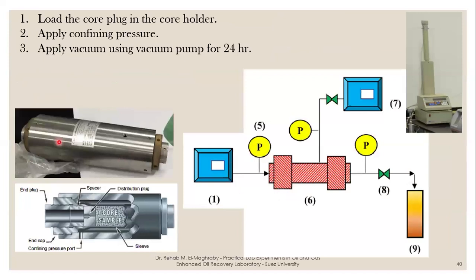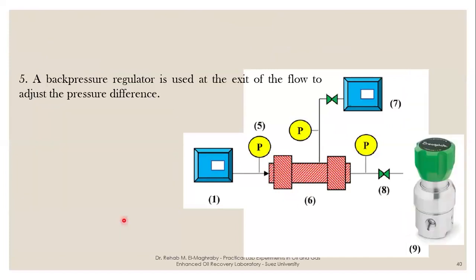So the first step here is to load the core plug, and then we apply confining pressure to prevent any radial flow, and then we apply vacuum to clean the core from any air because we don't want to have interference, especially if you have a liquid. The other step here is to inject the fluid that you have, and the last one that you apply, you change the back pressure, so you will get different pressure delta P.